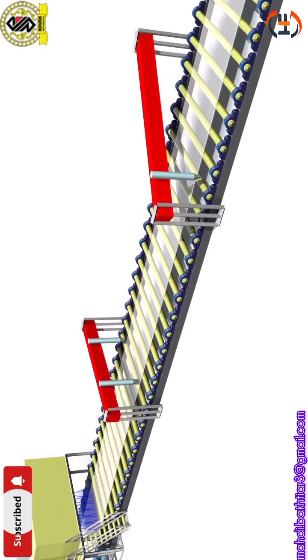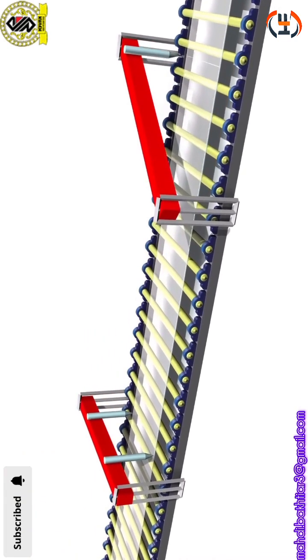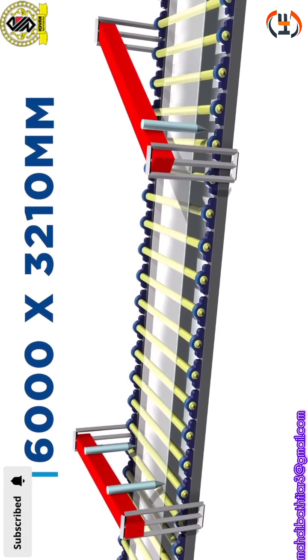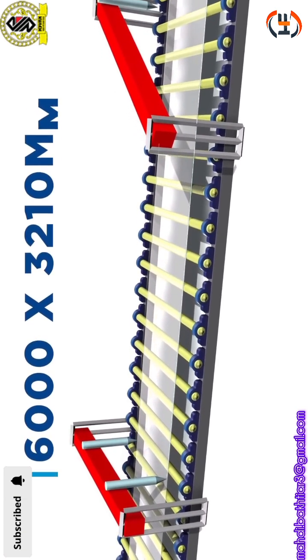Glass sheets are automatically created by a two-step cutting process in which the ribbon is striped and snapped along those strips to standard dimensions. The longitudinal stripes are made by a diamond wheel that creates surface defects on the glass. This prepares the ribbon for the subsequent cut of its edges, thereby removing the top roll marks and obtaining the net width. Then, the transversal stripes will determine the length of the glass plates.